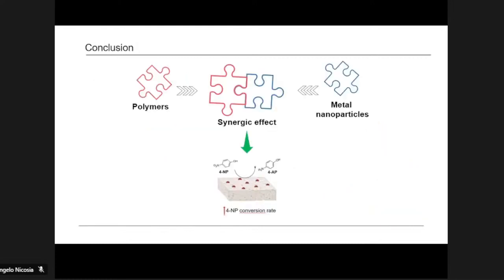So, at the end, the most important thing of this work is that we have observed a synergic effect of the polymers and metal nanoparticles, giving a novel hybrid catalytic system with an increase of the nitroaromatics conversion in water media.